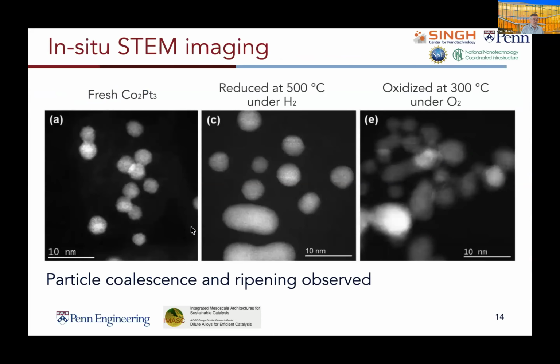If we look at images, we can go through and see how the particles change as a function of both reduction and oxidation. You see that in the initial stage, there's a relatively narrow size distribution, but upon reduction, we begin to see both coalescence. That's evident here from these two particles that have come together and sintered, as well as some evidence for Ostwald ripening, meaning that we have small particles and larger particles where the large particles are stealing some of the atoms from the smaller particles to reduce the overall surface to volume energy. Again, if we look at the oxidation, we see further coalescence and ripening occurring.